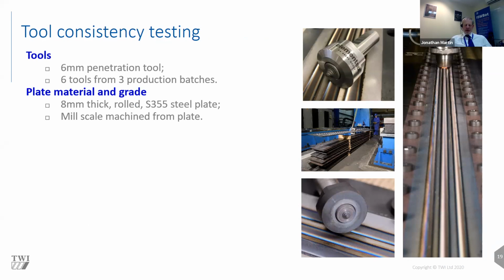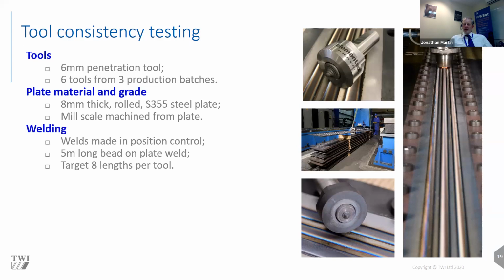The plate material that we welded was an 8mm S355 steel, low carbon steel, and we just took the mill scale off the top of these plates in order to reduce the number of variables, really, because we wanted to assess the tool material performance. All the welds were made in position control. So these were multiple 5 meter long bead on plate welds, and the target was to do 8, so accumulating about 40 meters of weld on each tool.